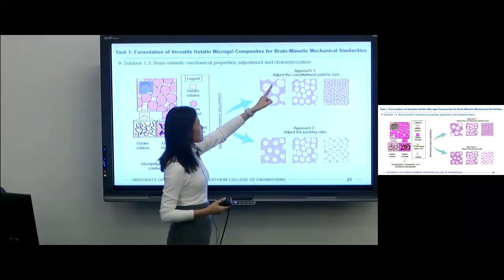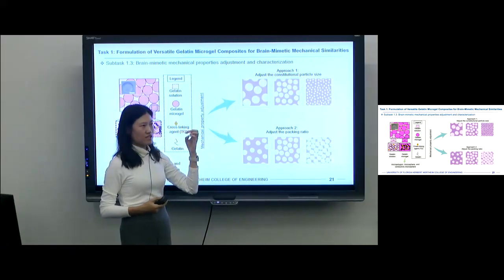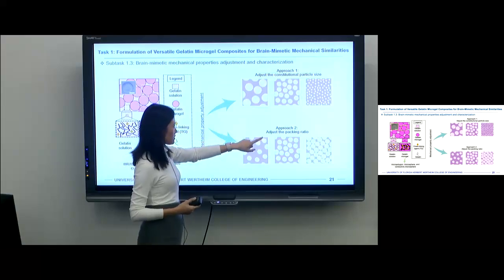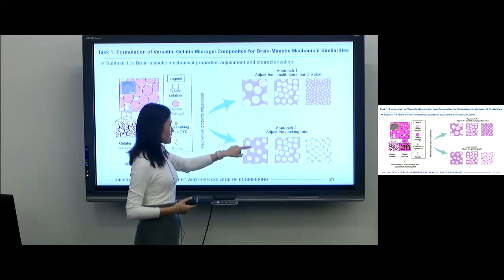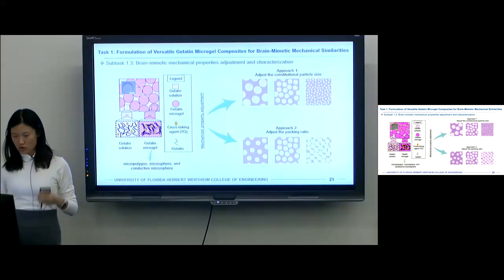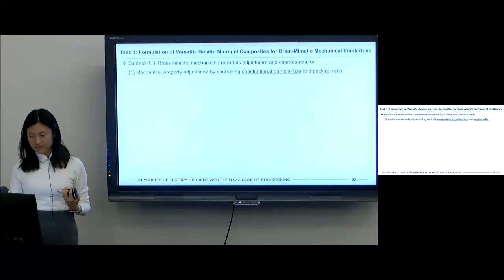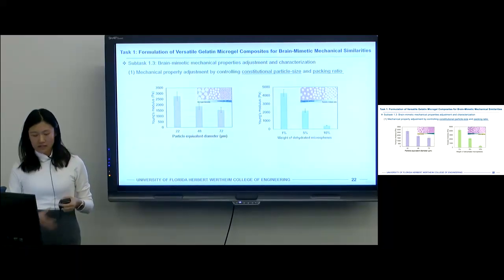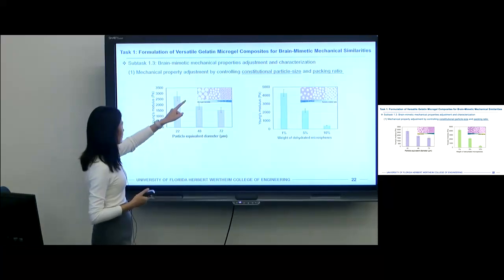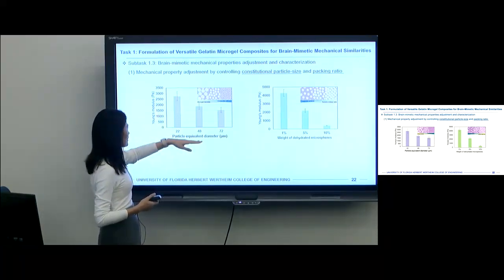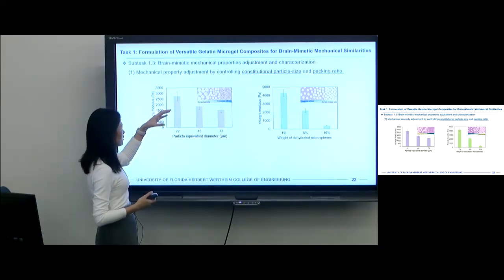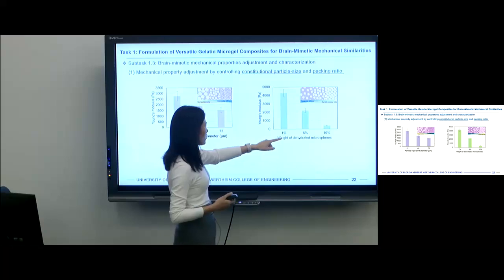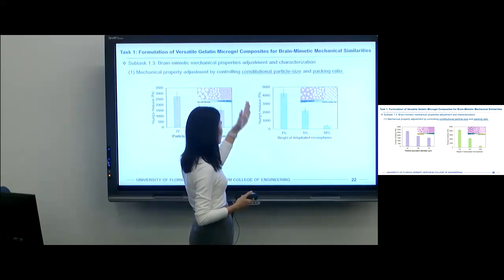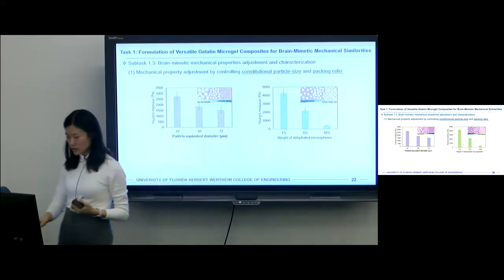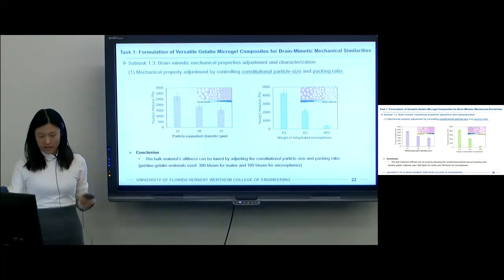So firstly, we can adjust the constitutional particle size with either the fragmentation time or the different parameters we controlled during the gel formation process. Or we can adjust the packing ratio between the gelatin microsphere and the gelatin solution. So using these 2 ways, we are able to control the mechanical property of the final composites. And here is the statistical results with decreased particle equivalent diameter. The Young's modulus of the composites will be decreased as well. And also with increased dehydrated microspheres, the Young's modulus can be also decreased. So in these 2 ways, we are able to control the stiffness of the final material.